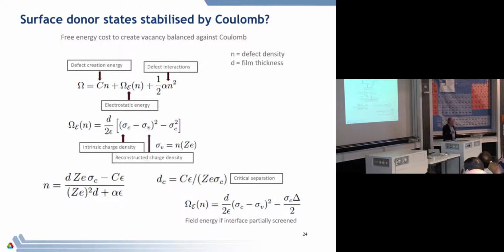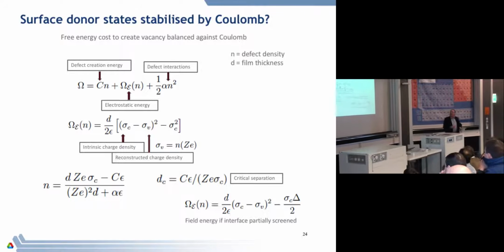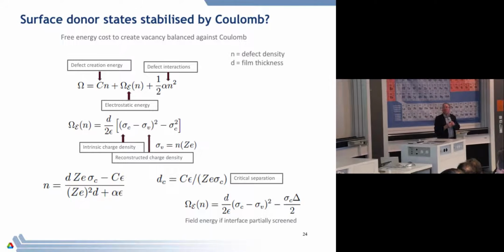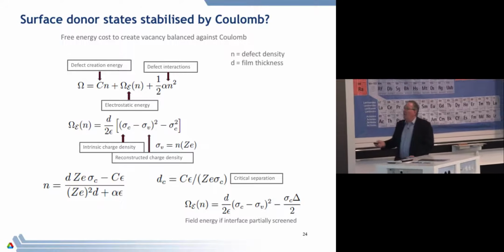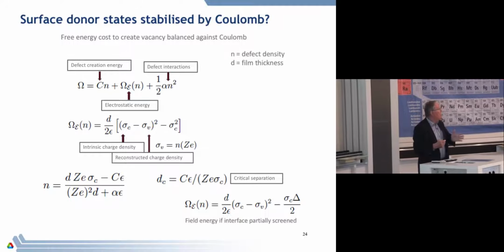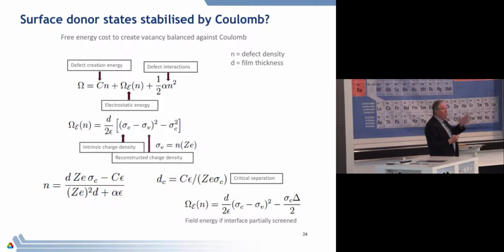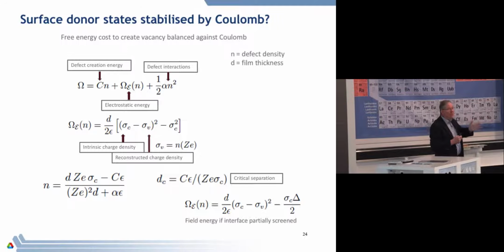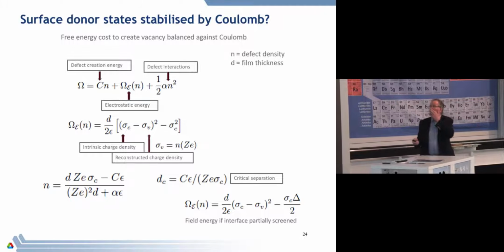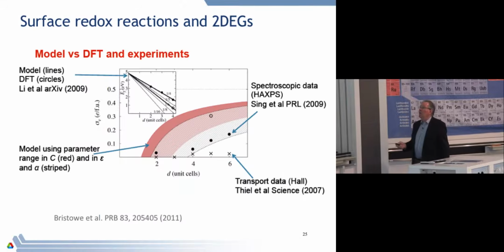That's done here, but you sort of imagine this in your head. There's a vacancy energy cost, there's a defect, there's a Coulomb cost, and there's a critical thickness that will turn up where it's favorable to have vacancies or other reactions forming at an interface which produce the doping and produce the screening. Okay. Where does that happen?